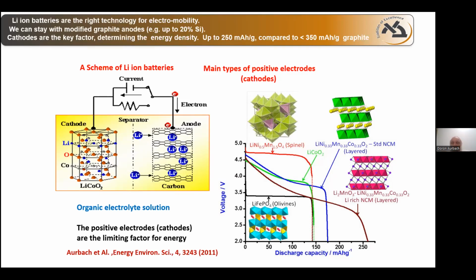3,700 milliampere hour per gram to nearly 370 milliampere hour per gram of graphite. So we gave up 90% of specific capacity at the negative electrode, but we gain a long life and safety. When the process is not lithium deposition, but rather intercalation of lithium into graphite, then we can have a better steady state situation.